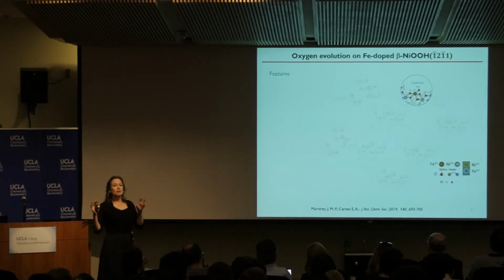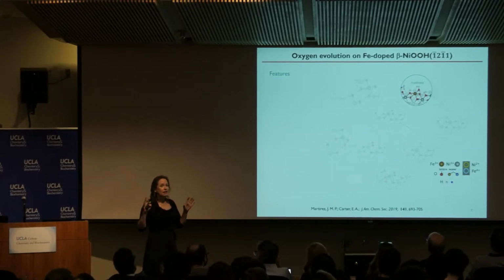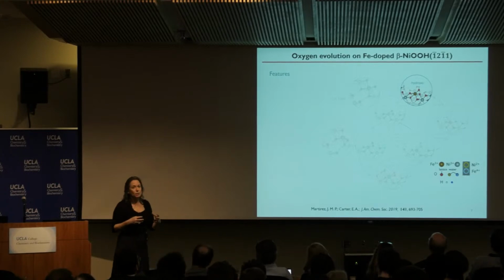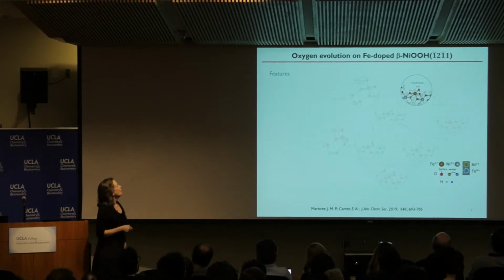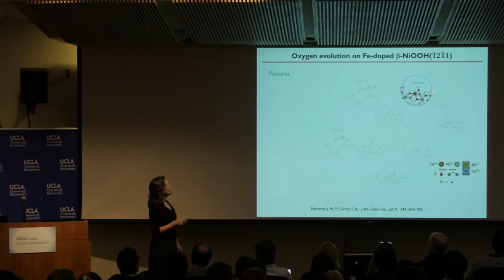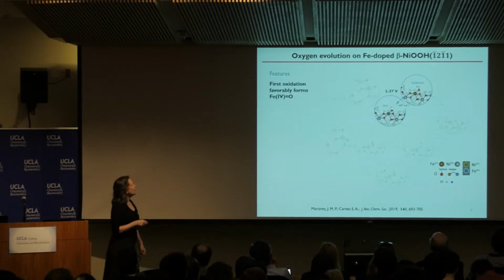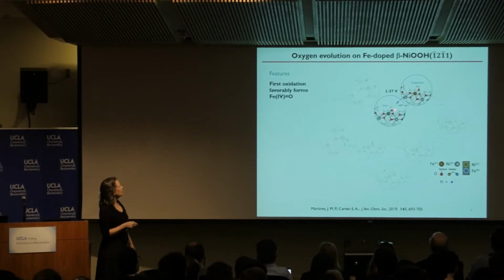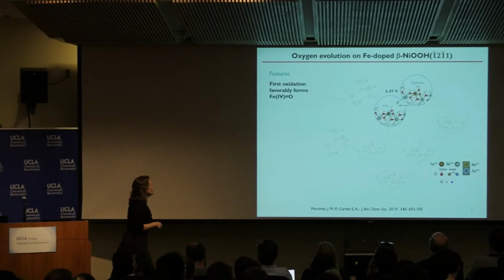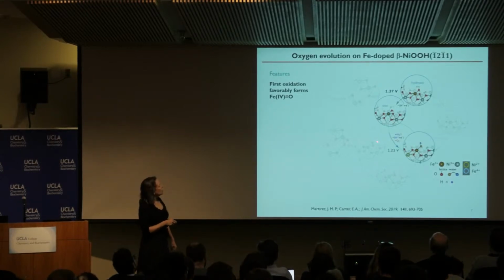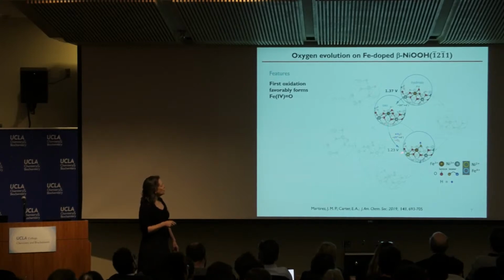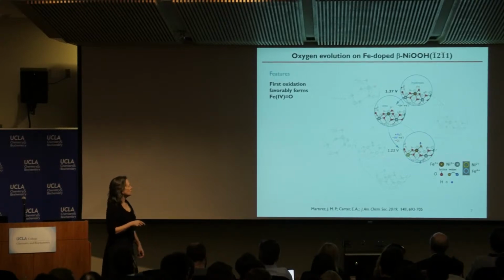So Mark did a lot of work to look at a whole variety of different possible mechanisms and then to try to sort out what was going on. And I'm going to just show you 2 slides about this. It turns out that what we discovered is that you start with this surface that has an iron hydroxo, and that iron hydroxo then can essentially get oxidized, losing a proton and an electron, to form this iron oxo. It's an iron(IV) oxo species, and then it undergoes further oxidation to release oxygen in the overall step to reproduce another state of an iron hydroxo.